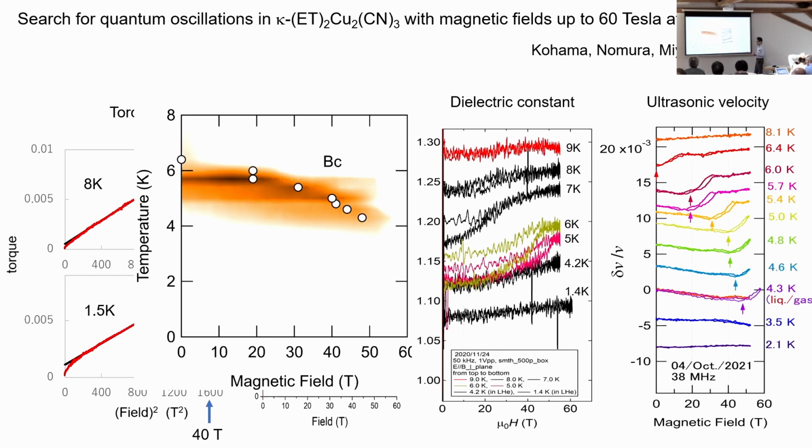So this is very consistent with our high field anomaly experience. Even at 15 Tesla, the spin gap-like behavior is very robust against magnetic field. So I think that this high field behavior suggests that this decrease of the paramagnetic spin susceptibility is a very unconventional phenomenon. But anyway,